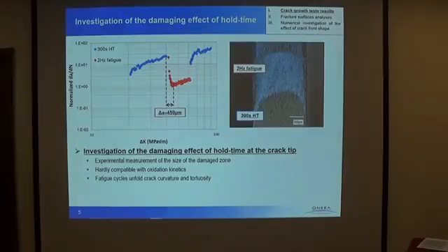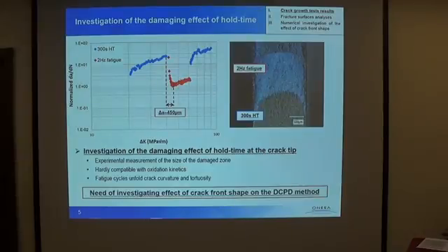Moreover, if we have a closer look at the fracture surface, we can see that under hold-time condition we have a large degree of crack front curvature, and it appears quite rough, I would say. While when we apply pure fatigue cycles, you can see that the crack curvature unfolds, and we once again get, I would say, almost straight through-thickness crack. And from this observation, we decided to investigate the effect of crack front shape on the crack growth rates measurement.